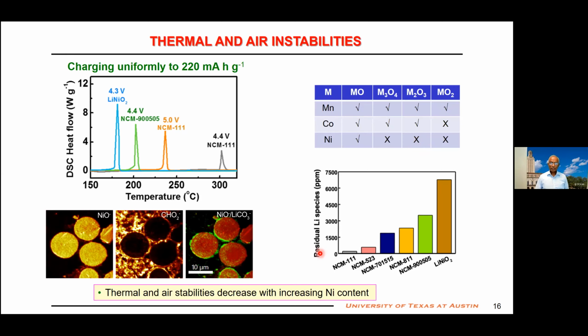There is something called the surface lithium hydroxide and carbonate, called residual lithium. You can measure it by acid-base titration. Here, the residual lithium is increasing exponentially. Actually, the three problems I mentioned, cyclability, thermal stability, as well as air stability, they all become exponentially challenging